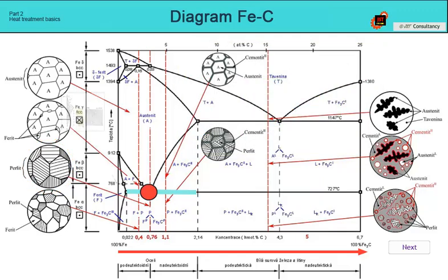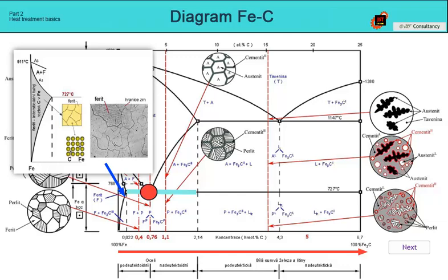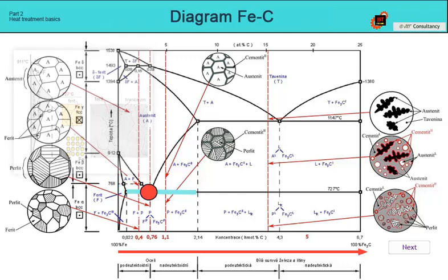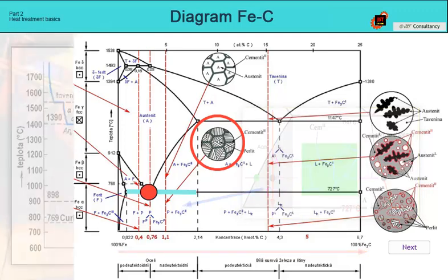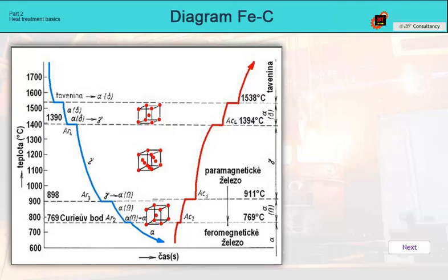The area of formation of pure ferrite is completely minor in steel, because the solubility of carbon in ferrite is very low. It is only 0.022% carbon. Therefore, the structure of sub-eutectoid steels is always made up of a mixture of pearlite and ferrite. In super-eutectoid steels, the structure consists of pearlite, as in the previous case, and so-called secondary cementite, expelled below the segregation temperature ACM. Iron is characterized by the fact that it changes its structural lattice during heating and cooling.